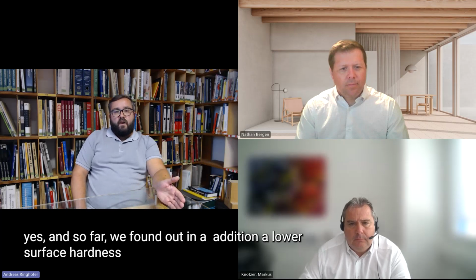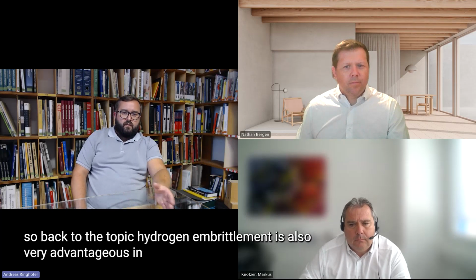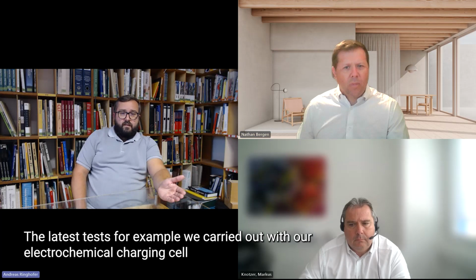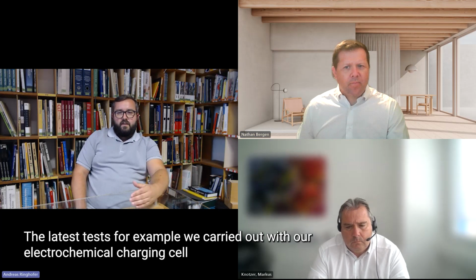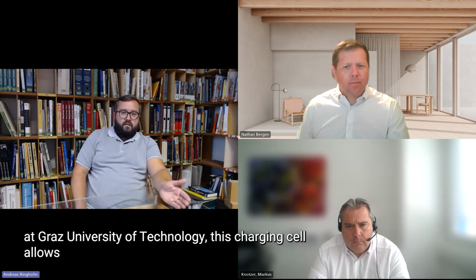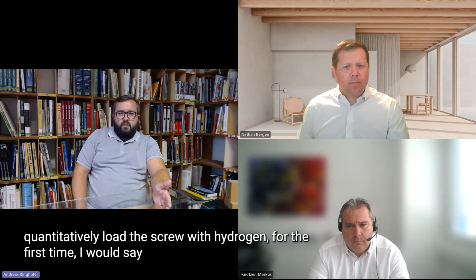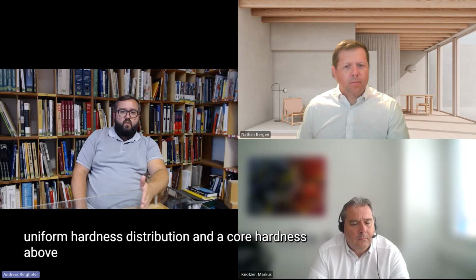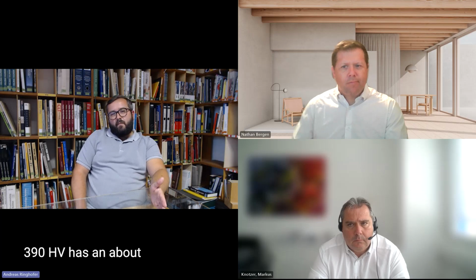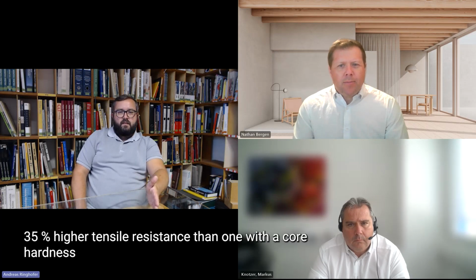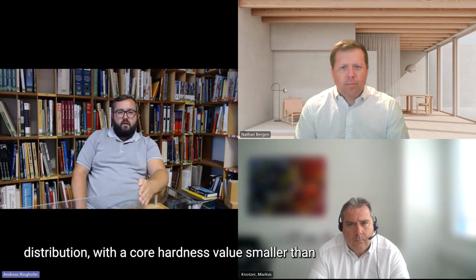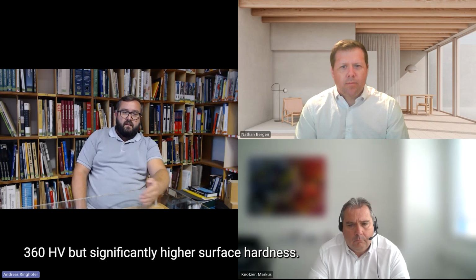Yes, and so far we found out, in addition, a lower surface hardness, so back to the topic of hydrogen embrittlement, is also very advantageous in terms of hydrogen embrittlement. The latest tests, for example, we carried out with our electrochemical charging cell at Graz University of Technology. This charging cell allows us to quantitatively load the screw with hydrogen for the first time, I would say, and led to the interesting result that a screw with a uniform hardness distribution, with a core hardness above 390 according to Vickers, has about 35% higher tensile resistance than one with a core hardness value smaller than 360 according to Vickers, but significantly higher surface hardness.